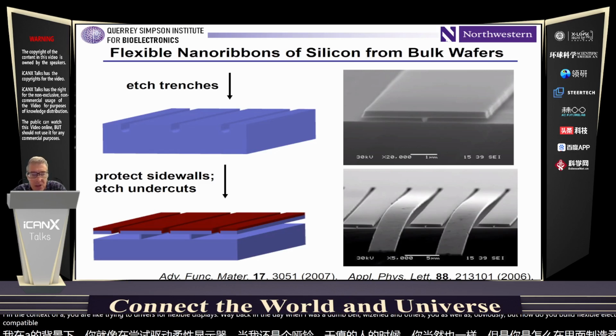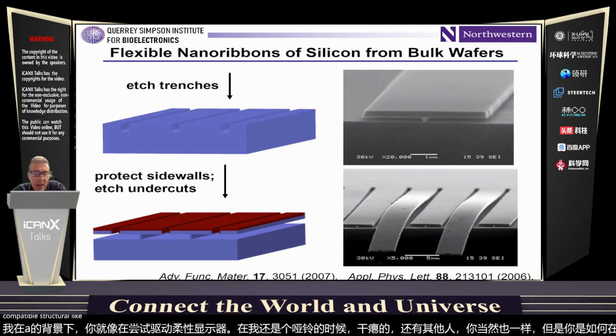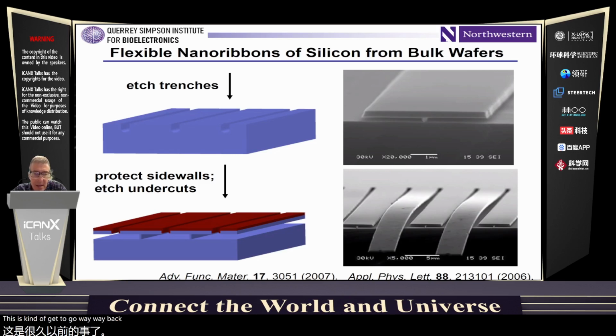We use anisotropic etching techniques to slice off the near surface region of a wafer, very thin ribbons of silicon, thin enough, in the 150 nanometer range, to support all the kinds of electronic functionality you ultimately need, but thin enough to be mechanically flexible so that they could be used as building blocks, as active semiconductor materials for devices you could build on a sheet of plastic or a slab of an elastomer, for example.